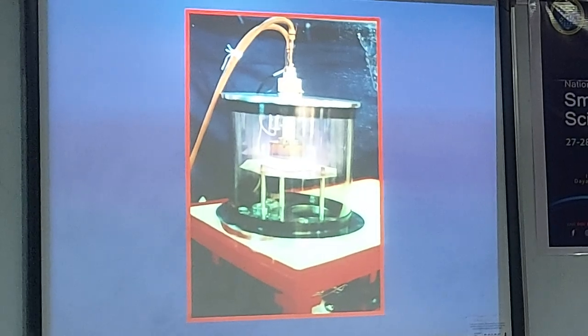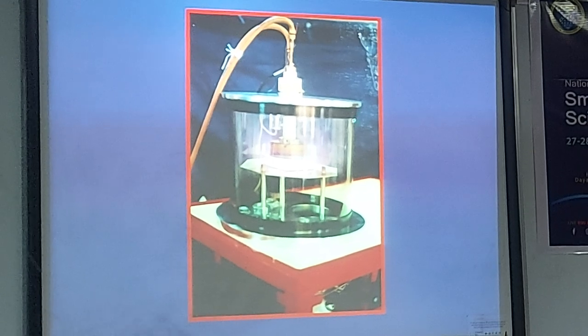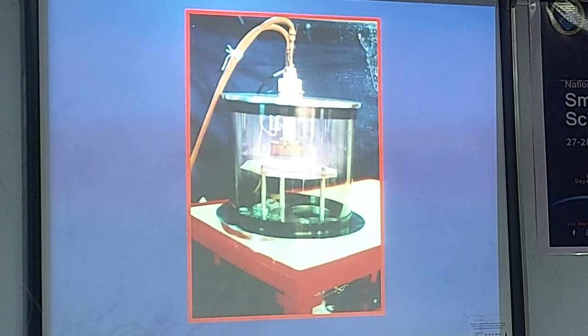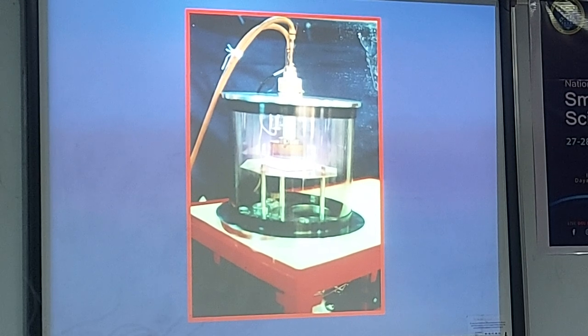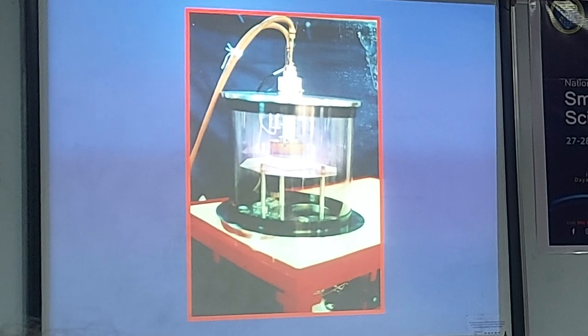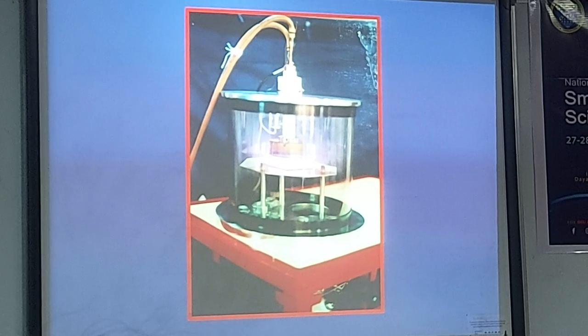And this is one of the earliest sputtering chambers that was made by my students in the laboratory. This is a chamber, this is a target, because whenever the ions hit the target, the target gets heated. In order to keep it cool, you continuously circulate cooling water. So this is a plasma that we see inside the chamber. Sometimes, especially for short metal deposition, a glass chamber is okay. But if you are going to do RF sputtering and sputtering for a longer duration, this glass chamber is not ideal. We go for a metal chamber so that we can do the deposition.